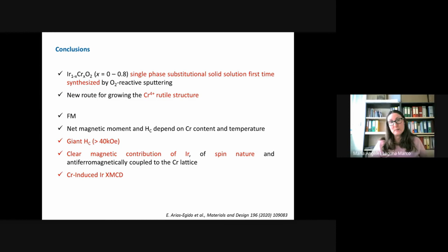So, to conclude, despite the difficulty of growing chromium dioxide by physical deposition techniques, a single-phase solid solution has been achieved by conventional reactive sputtering. Iridium, chromium, and oxygen crystallize in the rutile structure for an amount of chromium between 0 and 80%. Along the series, the oxidation state of chromium remains as 4+. And regarding the magnetic behavior, the diluted systems strongly depart from that observed in the parent compounds, chromium dioxide and iridium dioxide. In particular, by doping with iridium, the coercive field can be largely modified, achieving values up to 4 Tesla at low temperatures and even larger.